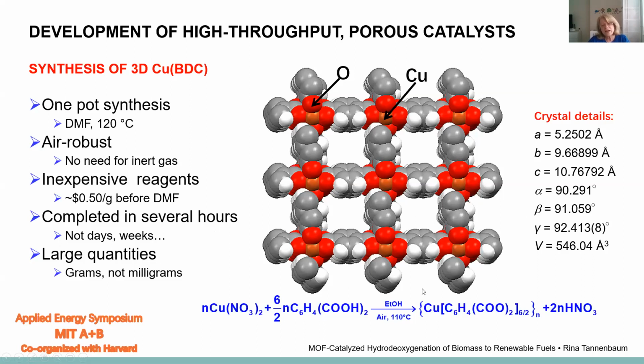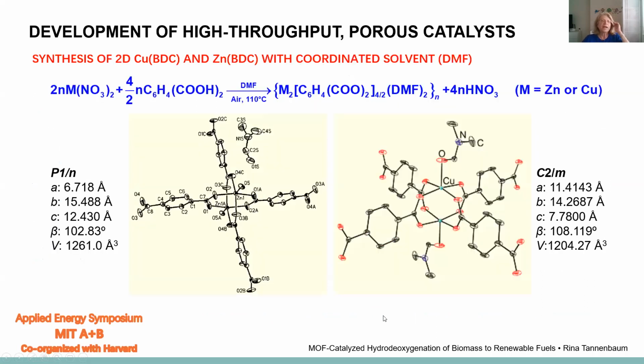Now, of course, this kind of geometry will be dependent on the ratio between the copper nitrate and the ligand. And so with different ratios, we can actually generate a different kind of geometry. And in this case, we can generate two-dimensional, both copper and zinc coordination polymers, or MOFs. And this is the crystal structure of the two types of complexes.